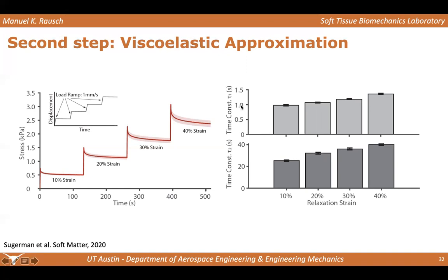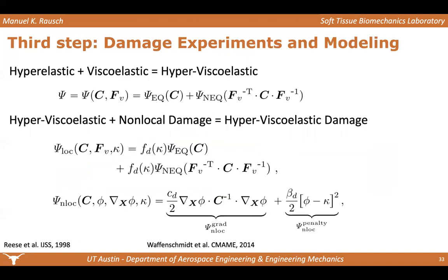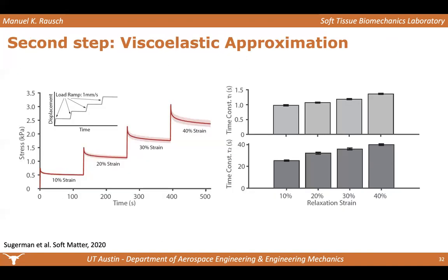And so our theory was that one could be driven by the poroelasticity, so the pressure gradient moving water and the water exchanging momentum with the surrounding matrix, and that momentum loss being responsible for some of the energy dissipation, and maybe a second mechanism that's more diffusion driven. We don't know this at this point, but that's something that we are starting to study and understand, or at least try to understand.